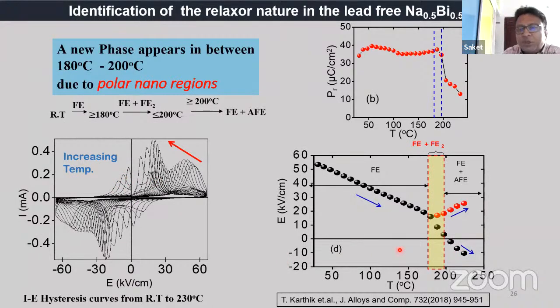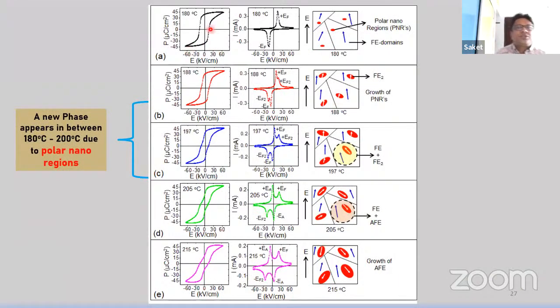I hope I was able to explain it so that you can get it. Otherwise, there are references where this is available in detail. You can go to them. So it is converted into this. This can also be shown with the variation of the remnant polarization with temperature, so this will be clear here. If you see this polarization plot, here this peak is there. Slowly you see two peaks coming. So we have explained that there is a ferroelectric domain and a formation of nanopolar regions with increasing temperature. These regions are also growing, and before a particular temperature they are in the same direction, so that's why this peak is on this side. After that they cross, and then this phase becomes antiferroelectric.